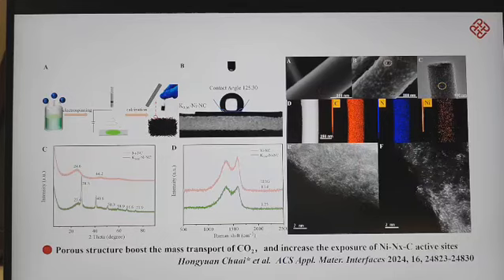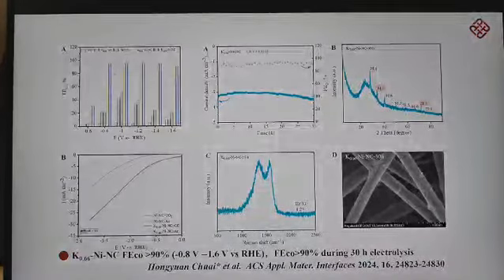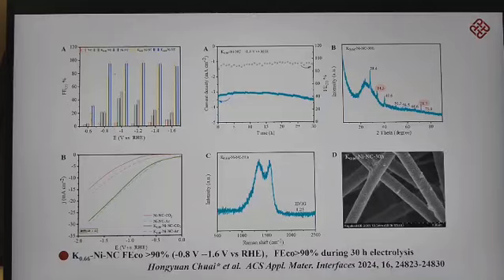This not only promotes CO2 mass transfer, but also exposes more nickel-nitrogen-carbon active sites. And then, we tested their electrocatalytic CO2 reduction performance in an H-cell. The results showed that the optimized electrode, potassium nickel nitrogen, achieved a CO Faradaic efficiency of more than 90% within a wider electrochemical window, and maintained a CO Faradaic efficiency of more than 90% during a 30-hour test.